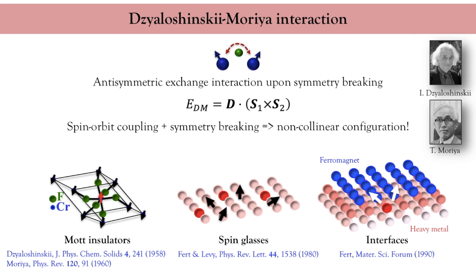The different exchange interactions we have seen, direct exchange, RKKY, super exchange and double exchange, all favor a collinear magnetic configuration, so either ferromagnetic or anti-ferromagnetic. In materials lacking inversion symmetry, an additional interaction emerges that favors perpendicular orientation of the magnetic moments. This interaction has been originally predicted by Dzyaloshinskii in the context of Mott insulators. It has been recently extended to spin glasses and most importantly to interfaces. This interaction favors non-collinear configurations such as spin spirals or magnetic skyrmions.